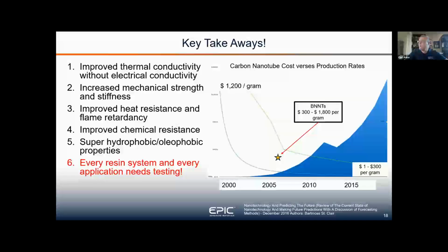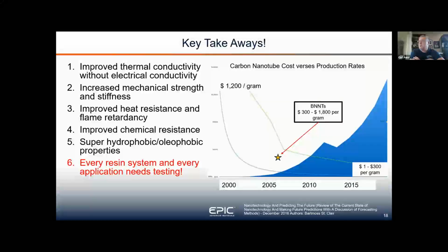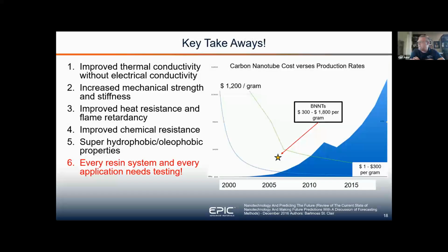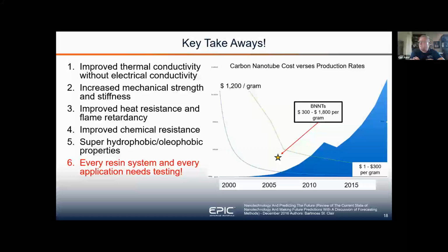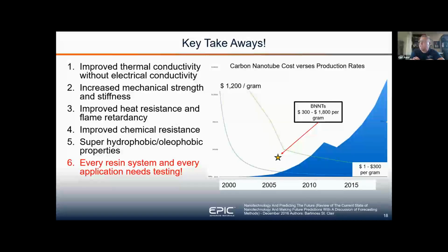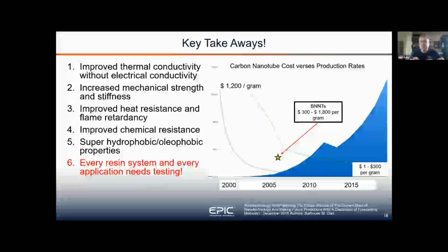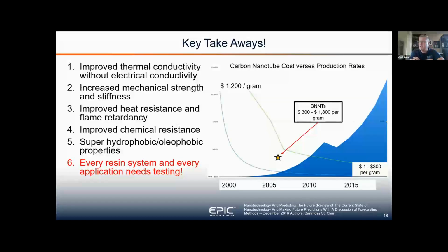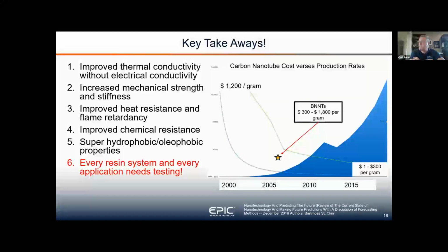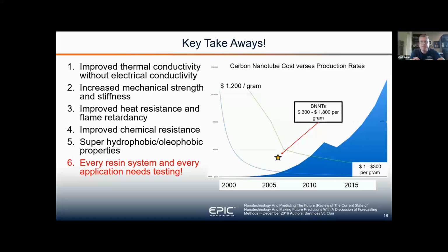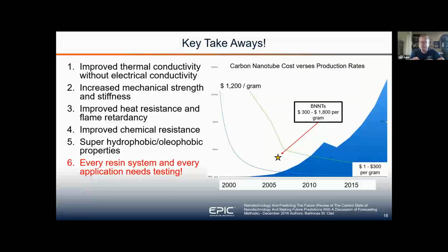What's the money? Well, carbon nanotubes versus production rates. Historically, in 2000, they were $1,200 a gram, and now they're around $1 a gram. And BNNTs, we believe we are right around $300 to $1,800 a gram, depending on the level of purity. So it gives you an idea that historically, we're about at 2005 with BNNTs, both in level of production for commercial applications and the cost of the materials currently. But we foresee that coming down with the higher production levels.